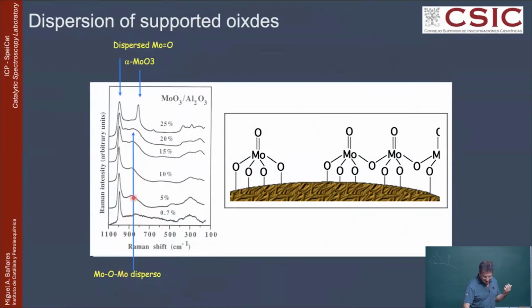Yeah, this is the dispersed molybdenum oxide. This is the molybdenyl bond, Mo=O, at about 1,000. And as you increase the coverage, it will increasingly polymerize, so this Mo=O bond slightly shifts to higher frequencies because of the polymerization. You also see the bridging oxygen, Mo-O-Mo, over here. You get more and more because it is increasingly polymerized. That is happening up to 20 weight percent molybdenum oxide on alumina.